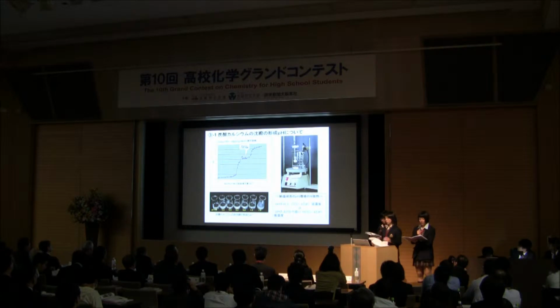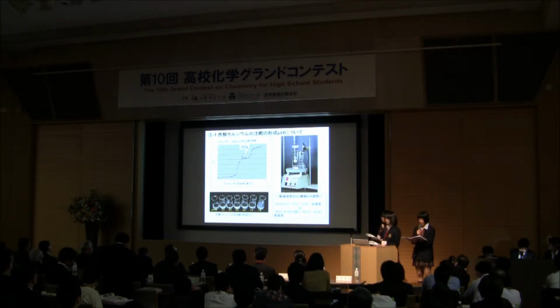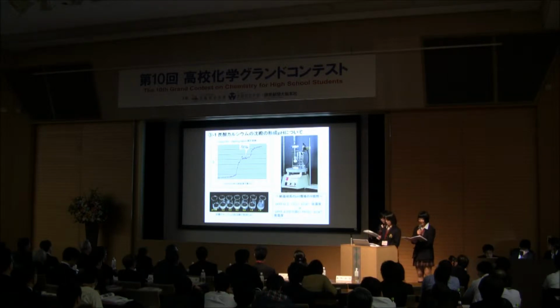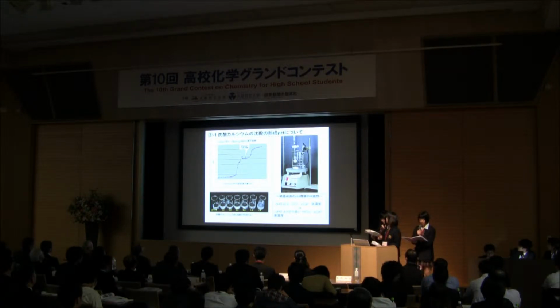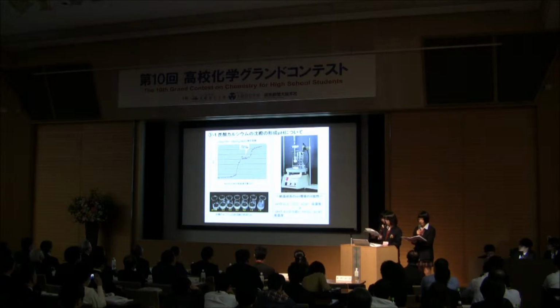Next, we considered what kind of deposit of calcium carbonate occurs at a defined pH level. We mixed these 2 solutions. One is CaCl2 with HCl. The other is Na2CO3 with NaOH. In these 2 experiments, we observed that the calcium carbonate deposit appeared at pH 8 solution.